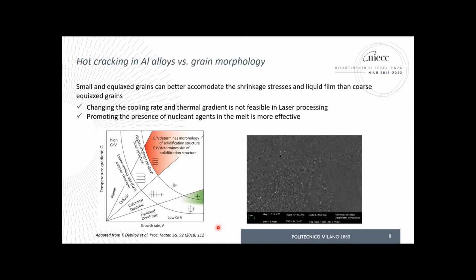The second strategy concerns the shift in the grain morphology from columnar grains towards at least equiaxed grains. So again, this is a very standard chart showing in a qualitative way the trend for the generation of different structures depending on the solidification conditions. On the y-axis, we have the temperature gradient. On the x-axis, we have the growth rate of the solid front.